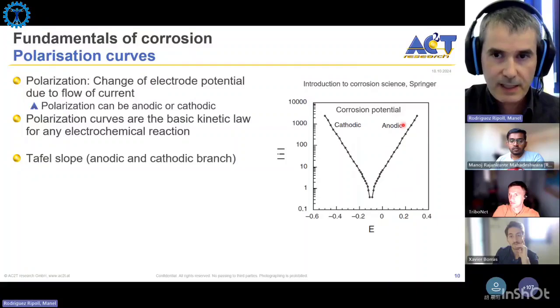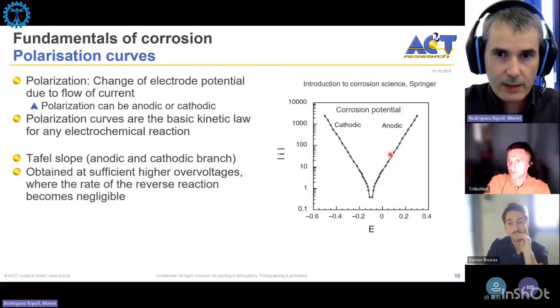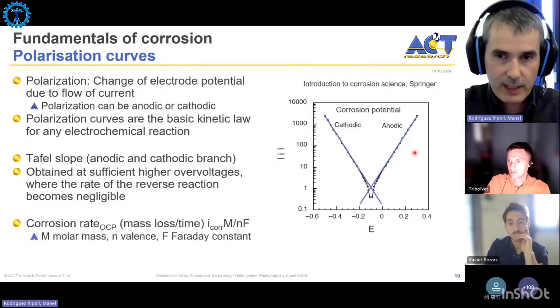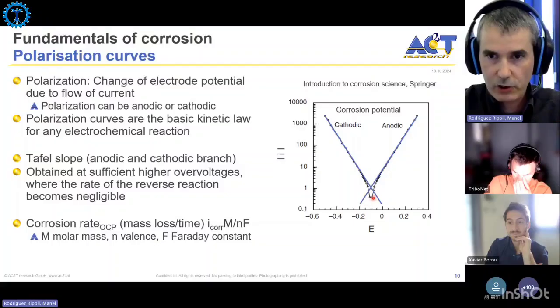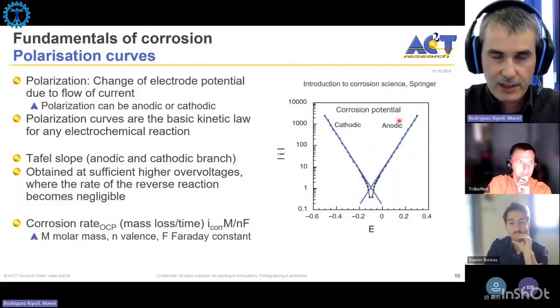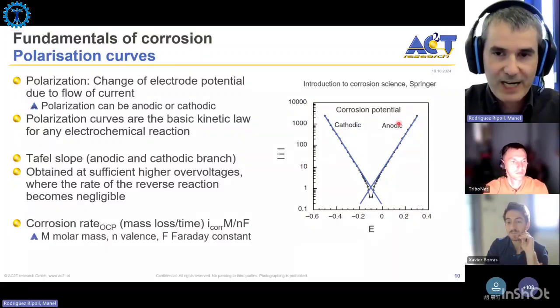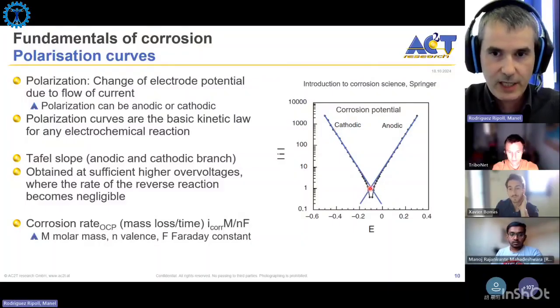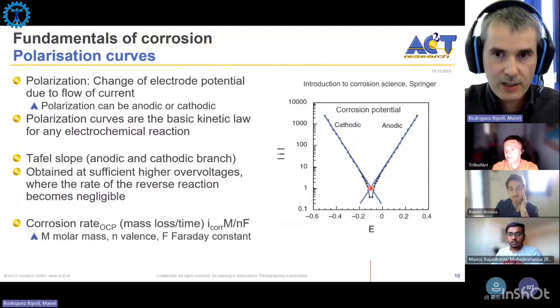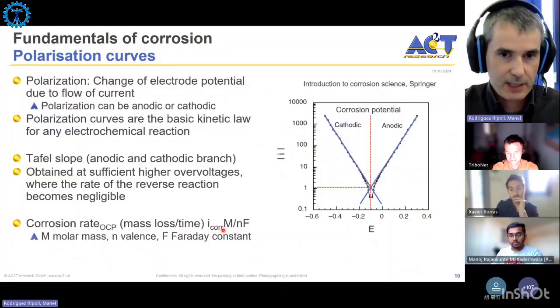So basically we see that there is a regime here and here in this semi-logarithmic scale, where the current is related to the potential in the semi-logarithmic form. And if we take the extrapolations, for example, here and here, we can calculate the corrosion potential. We can see that close to the corrosion potential, these branches are not linear anymore. This is because here the anodic reaction dominates, here the cathodic reaction dominates, but here you have both of them simultaneously, so you cannot neglect the other one, and this curve becomes nonlinear. But if you take the extrapolation, you can get here the corrosion potential, and if you get, for example, the corrosion that occurs at the corrosion potential, you will get the corrosion rate of that material in that electrolyte under open circuit conditions.